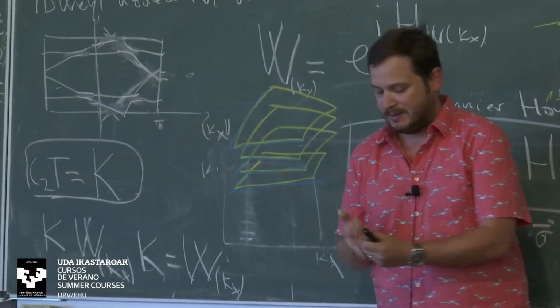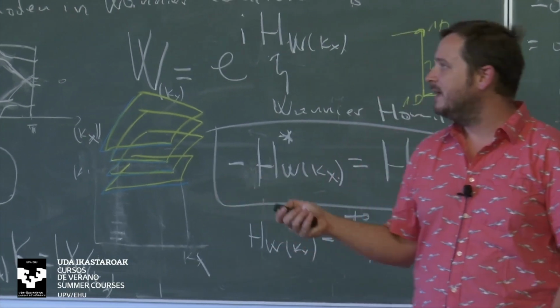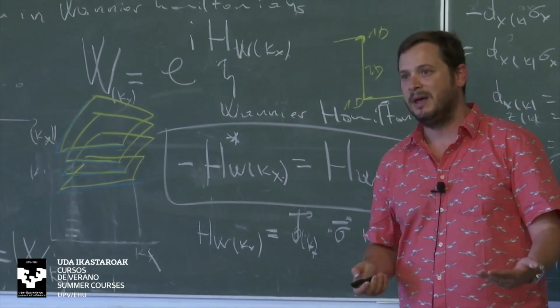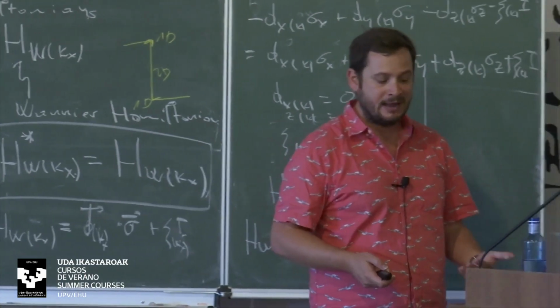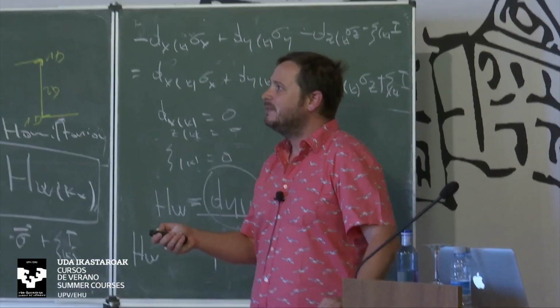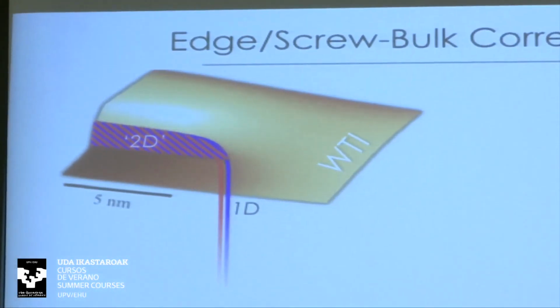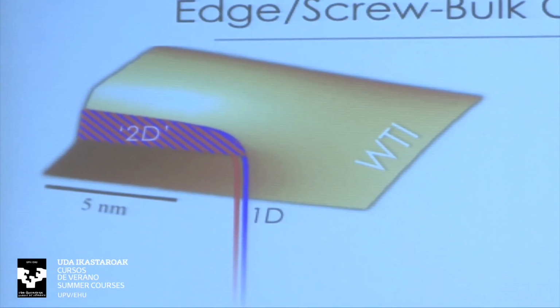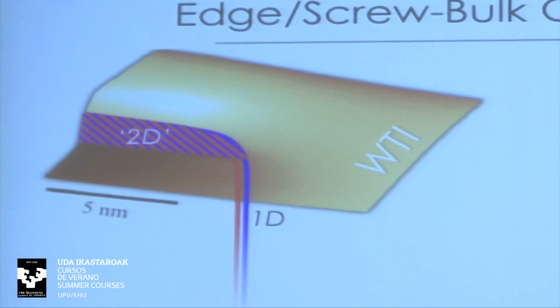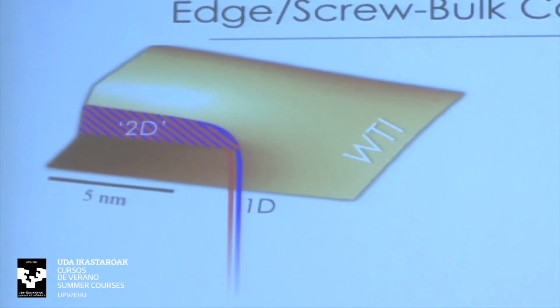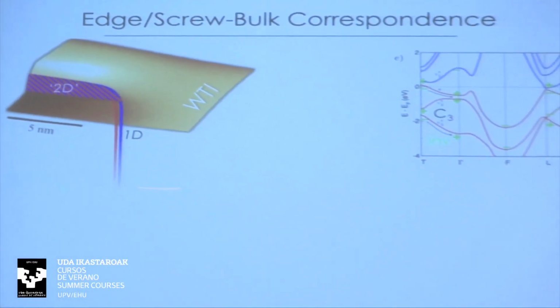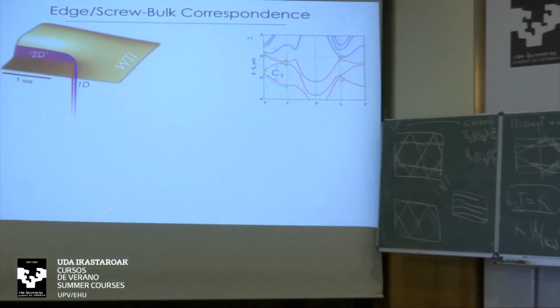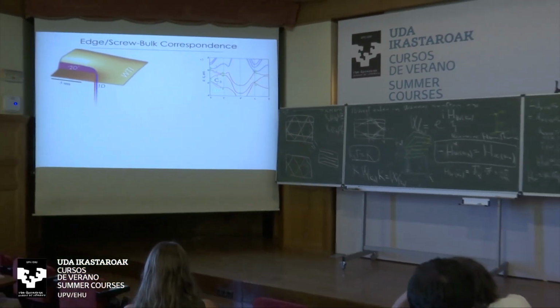Basically this minimal 2D side facet, which is made out of a bismuth bilayer, which was classified as a 2D TI before, is the helical mode of this 2D TI. But then instead of just having layers, we cut halfway through, we shift them, we glue together, and we kind of get a 2D TI which wraps around itself in a loop-like structure, and this helical mode is just winding down along the screw axis until it gets to the bottom surface.